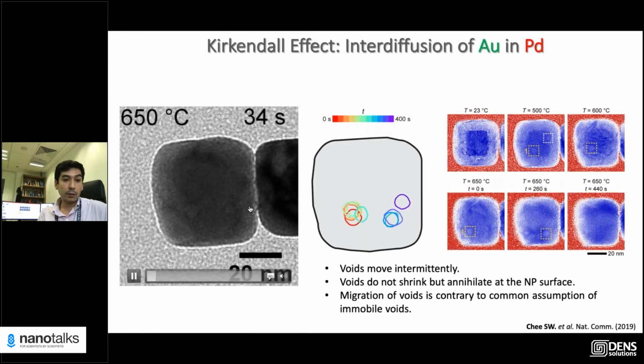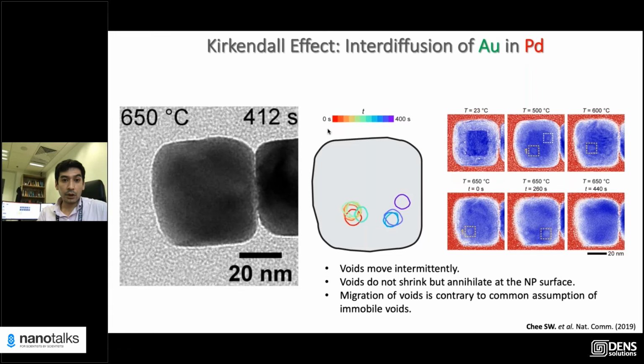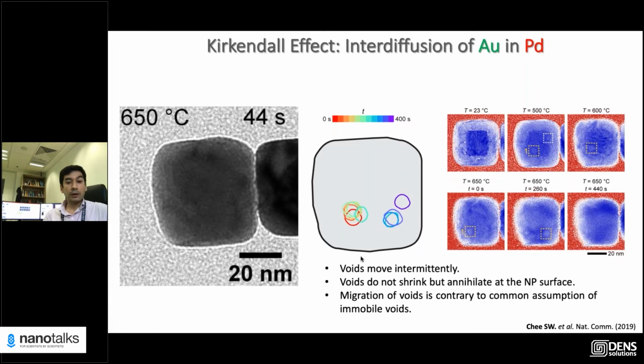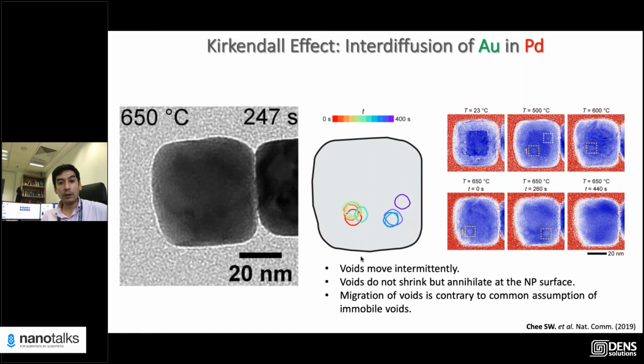So this is one of the movies. I don't know if you can see it, but there are voids forming, and as you see, these voids are quite easily moving around, right? This tracks the position of the void as a function of time. They're jumping around. So this already shows you that voids are not stuck. They actually diffuse, or move around. And this motion is intermittent, right? They jostle around and then jump, and jostle around and jump.